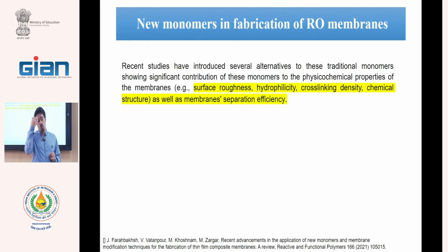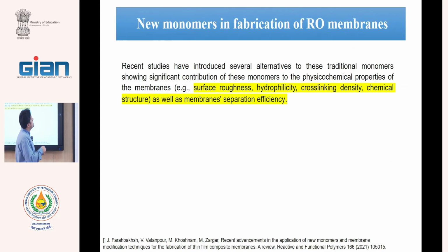Therefore, we must remove chlorine before the RO. But in most water and wastewater, for disinfection, we must add a very low amount of chlorine. Therefore, we will have chlorine in the feed of RO, and this destroys the membrane and reduces the long life of the membrane. Therefore, membrane researchers suggest new monomers for reducing surface roughness, increasing hydrophilicity, increasing cross-link density, and others.